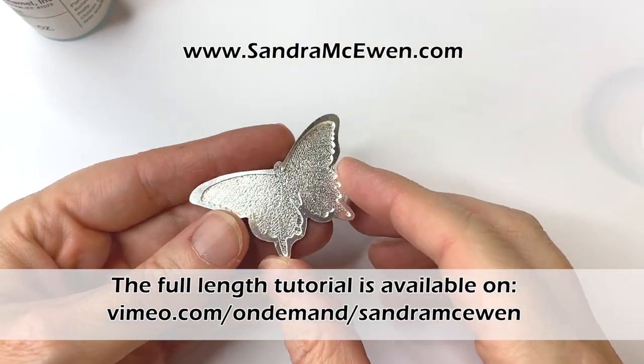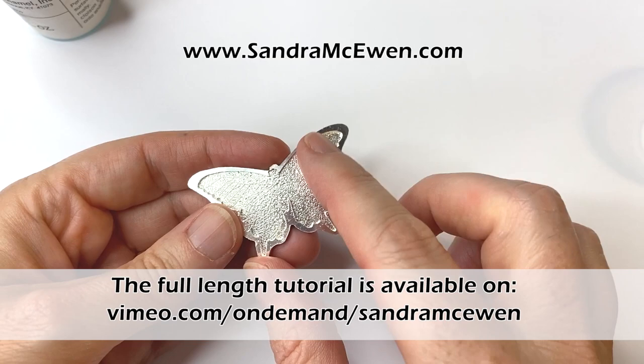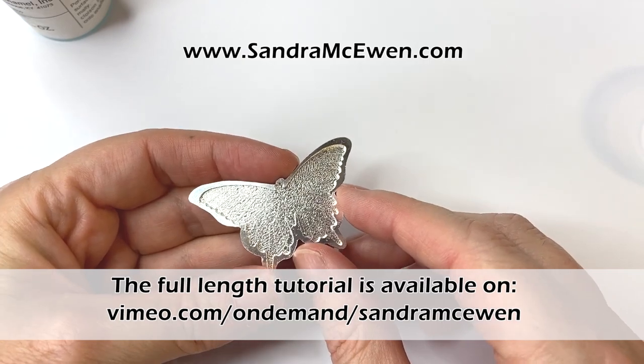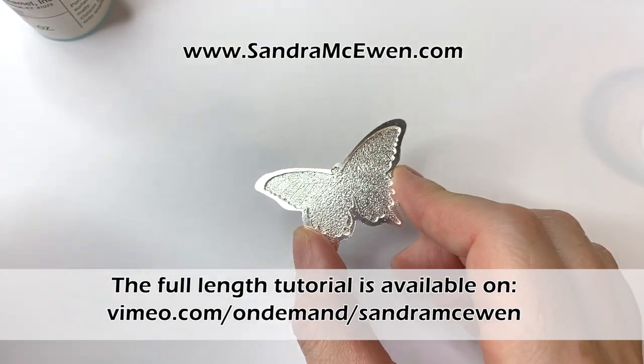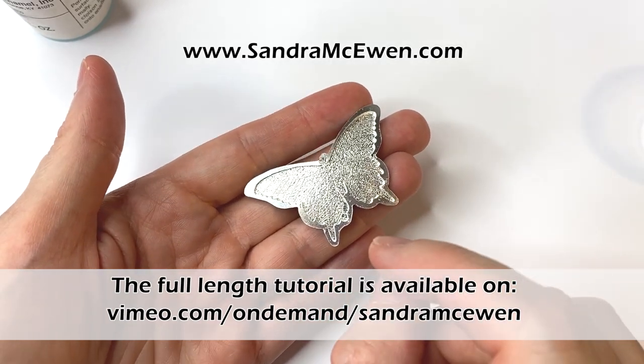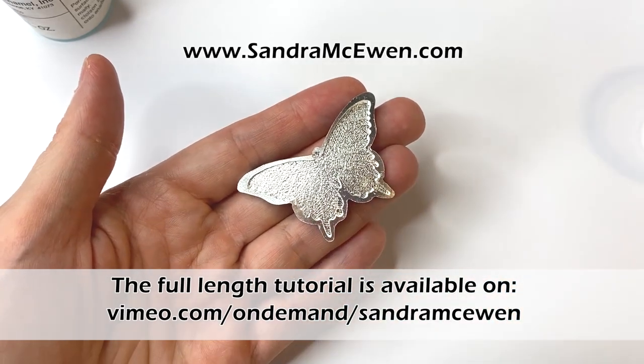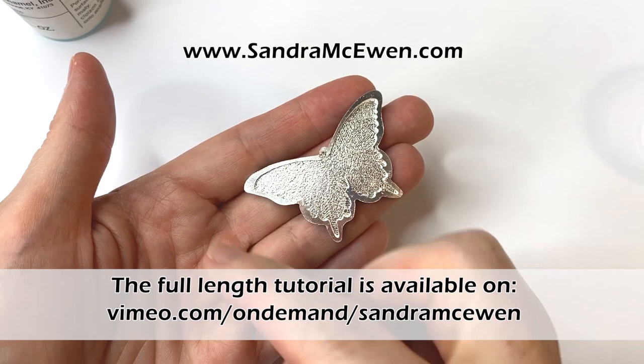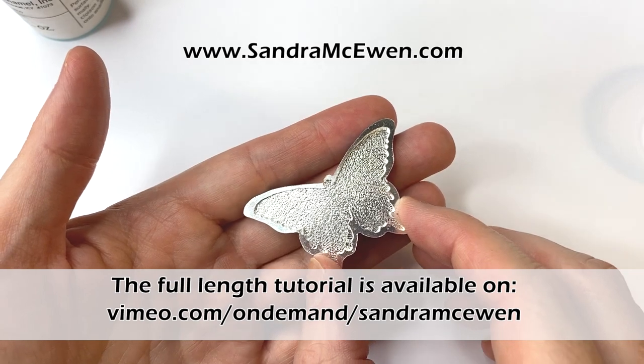This came out lovely — it's nice and even. As I said, it's a thin coat, so it's always going to look a little bumpy in texture, but that is perfectly fine. There's no yellowing — it's a really nice coat of flux. The G110 is a good flux. If you find trouble and pull it out and the whole thing looks very, very yellow, it might be that you've under-fired it. So put it back in the kiln and give it a really good long soak until almost the trivet is red hot, then pull it out — chances are that yellow will clear up, because under-firing is also a reason flux goes yellow.